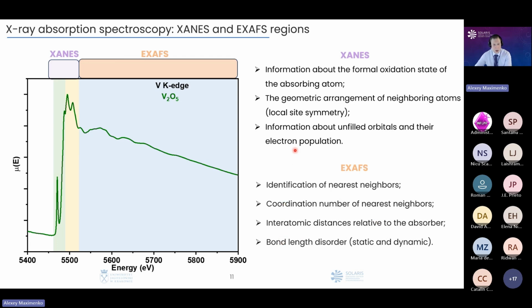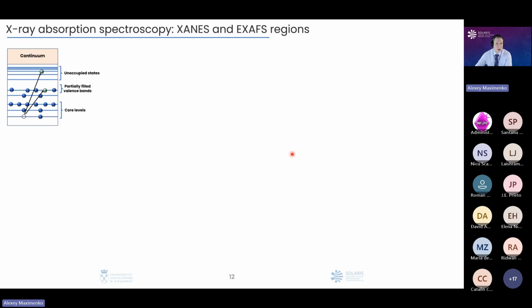In order to understand how we could get the information, let's go to the basics. It is understandable when we investigate the XANES region, in this XANES region we excite our photoelectron to unoccupied states. It means that we investigate what the structure of the states in our material is. That is how we could get information about the electronic structure. But when we excite our photoelectron to the continuum, here a quite interesting effect appears. Imagine that we have our absorbing atom, and we excited a photoelectron, let's say from the K shell to the continuum.